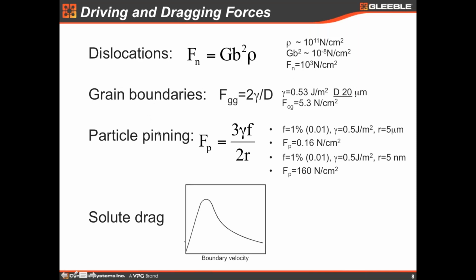One will be the particle pinning. And this is the equation. This was derived probably in the 50s, by 1949, I think, by Zener. So this is the Zener pinning, some people say. And this is, again, the grain boundary energy, the volume fraction of precipitates or particles, and the radius of the particles. Very interesting that for the same volume fraction, if you have a 5 micron particle radius versus 5 nanometers, we see that there's a big difference in this dragging force. So this also prevents recrystallization to progress.